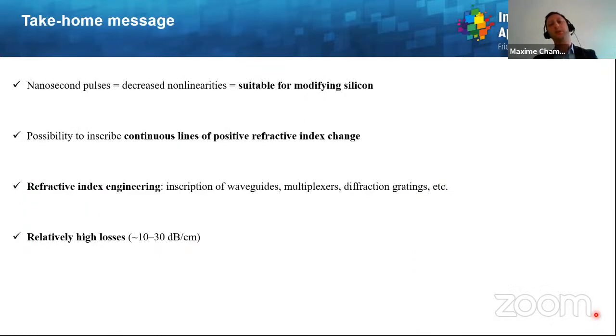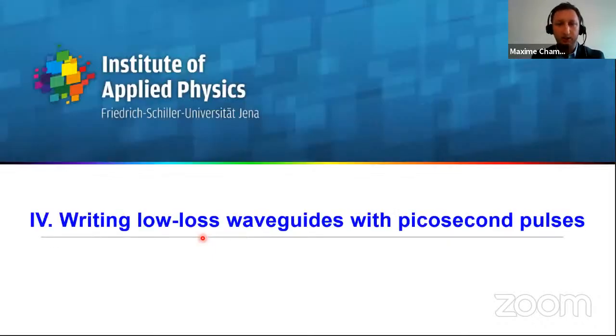So here is the take-home message for this part. With nanosecond pulses, we have decreased nonlinearities, meaning that it is suitable for modifying silicon in the bulk. It was possible to inscribe continuous lines of positive refractive index change. The refractive index engineering endeavors allowed us to demonstrate that it is possible to write long waveguides, multiplexers, and diffraction gratings. However, the losses were relatively high. And this is one point we addressed afterwards by endeavoring some picosecond laser irradiation for waveguide writing inside silicon.